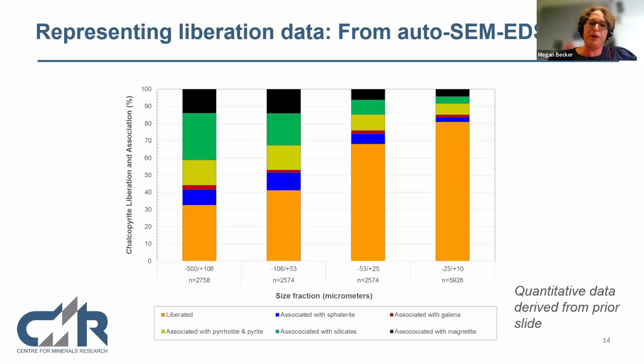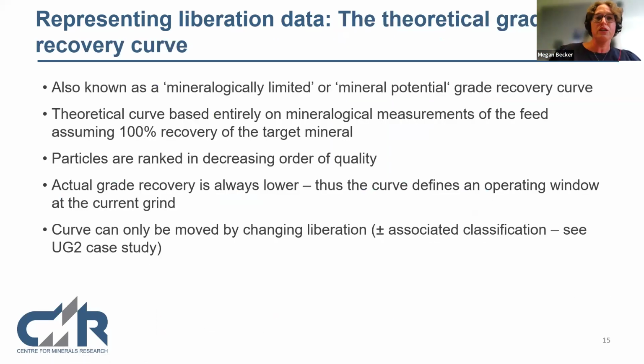One thing to just describe here: when I report something like association, to capture the liberated particles, I would have used a descriptor that says the area of chalcopyrite in that particle is more than 90%. And then I want to understand, of all the particles that have less than 90% chalcopyrite in them, what is the relationship of that particle to the mineral on the perimeter? So what minerals sit next to it? And then obviously that is quantified, and that's how I've got this association. So the liberation here is reporting something about an area measurement, and the association is telling me about the perimeter characteristics of the particle. Okay.